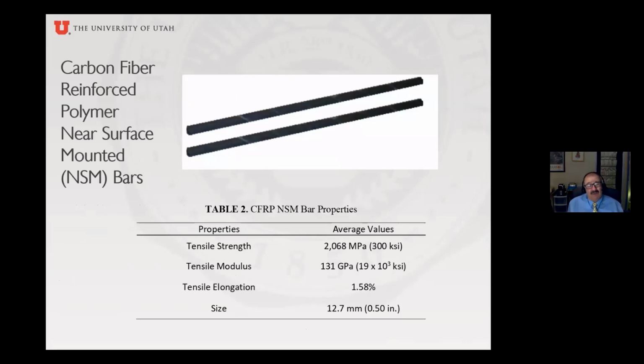We also used, for our second retrofit, carbon fiber reinforced polymer near surface mounted bars. These look like fiberglass rebar, but they're actually carbon fiber. And they have high tensile strength, 300 ksi. That's almost 5 times stronger than steel. Tensile modulus, though, is a little lower than steel, 19,000. Steel is 29,000. Tensile elongation is the biggest problem, 1.6%. For example, steel bar can go up to 10%. So it's a little bit low for strain. And these carbon fiber bars were about 1/2 inch diameter.